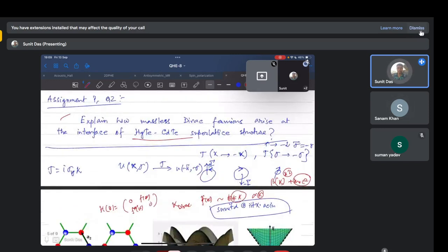Now in HgTe also, if we have this kind of Hamiltonian analytically, we can solve it at some high symmetry point. We just expand those functions and see what happens, and then we can arrive at those expressions. But I think it's a numerically calculated band structure. As you increase or decrease the thickness, there is some critical thickness of this HgTe, CdTe quantum well, and around that critical thickness you will have Dirac or linear band crossings.